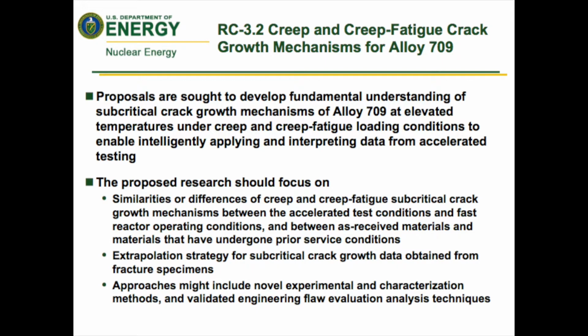Proposed research should focus on, again, similarities and differences of creep and creep fatigue subcritical crack growth between the accelerated lab conditions and the fast reactor operating conditions, as well as between the as-received materials and the materials that have undergone aging in service. Extrapolation strategies for the crack growth data obtained from the fracture specimens in the lab need to be developed for application into the field. And once again, we're looking for approaches that might include novel experimental techniques and characterization methods, as well as validated flaw evaluation analysis techniques. That's really all I had to say in prepared remarks, but I would be glad to